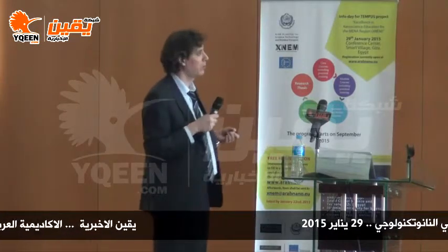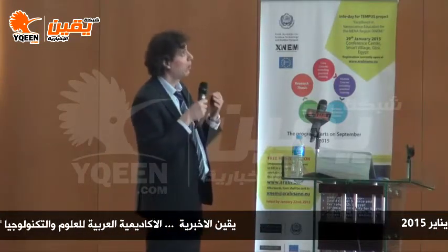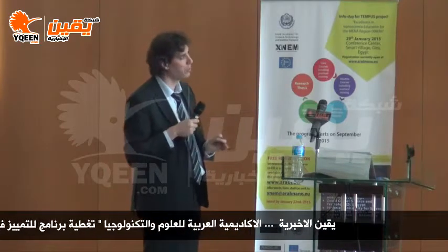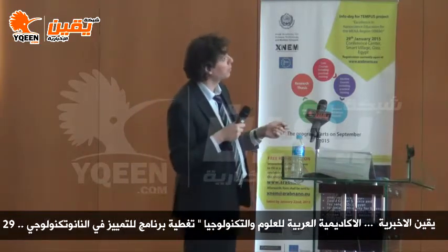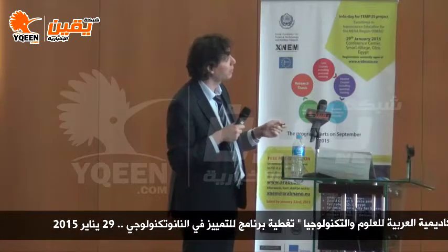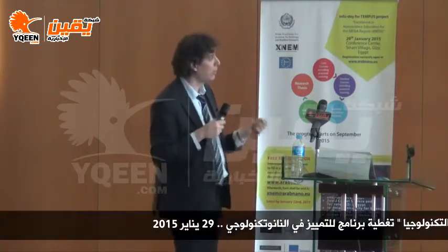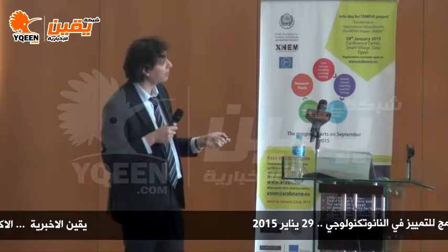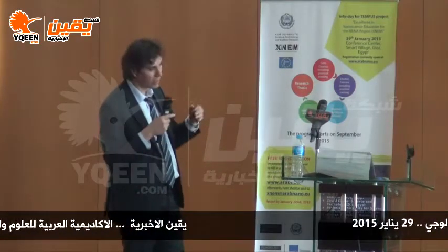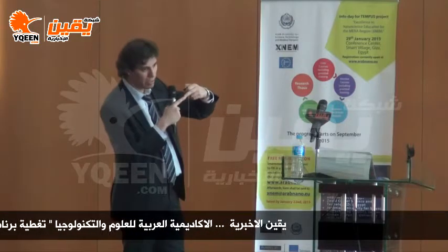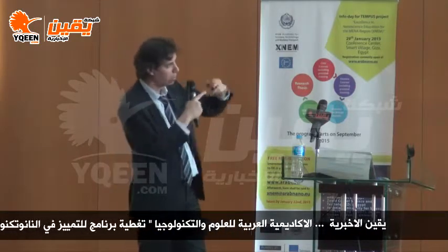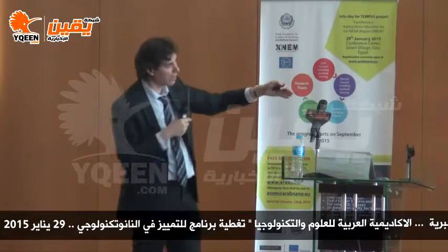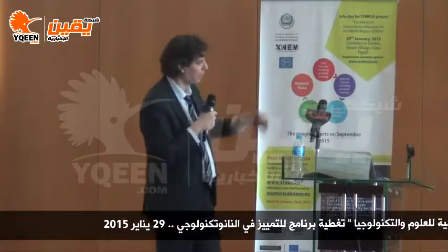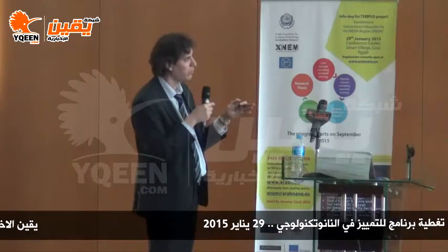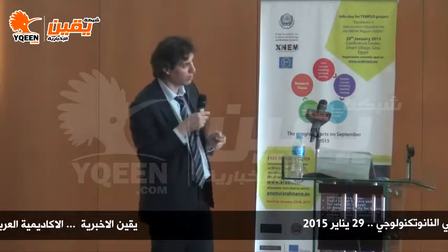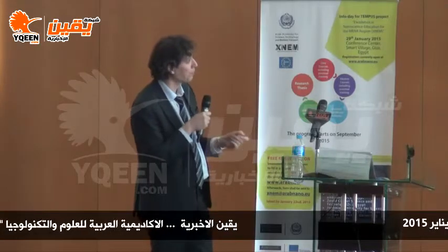If you want to devise electronic devices, you have to be able to process your material to have very stable properties. So this is the band structure of graphene, which doesn't show any gap. I mentioned gap earlier. So here, this is the schematic. You can see that the valence band and the conduction band are conical, and they join at a point. Normally, in a semiconductor, like I mentioned before for diamond, you see an energy gap. That's not the case here. And that's actually one of the main obstacles for graphene that we try to circumvent with nanotechnology and also heterojunctions.